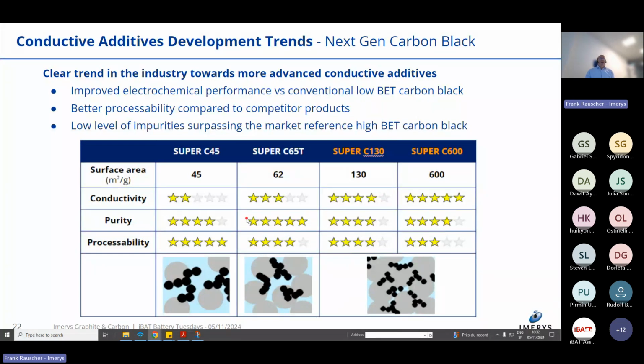Now, going into development trends for conductive carbon black. I mentioned that before. What customers are looking for is high conductivity at low loadings, low addition rates. And you can achieve better conductivity by increasing the surface area of your conductive carbon black. You see here another grade that we sell, Super C45, Super C65T.